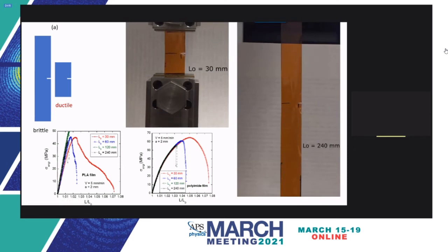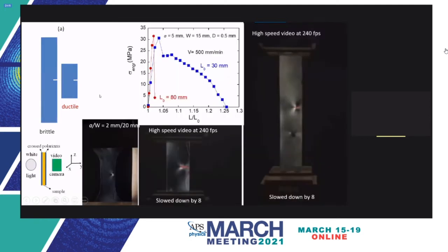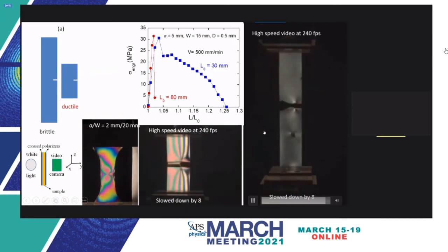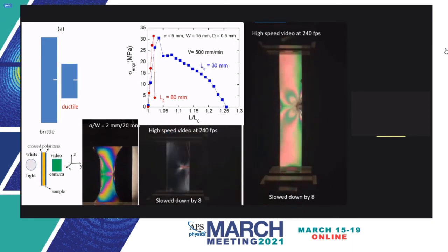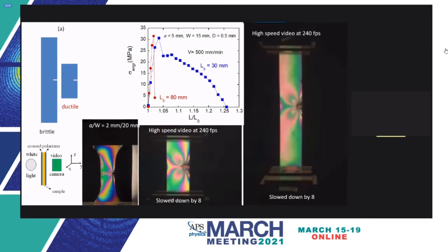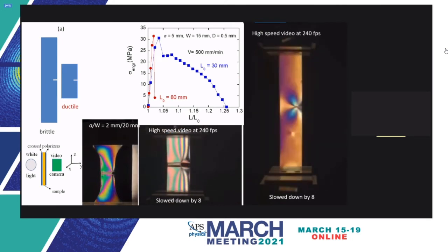Well, we have no time to explain why we think this is the case. So let's look at this problem a little further by taking a piece of polymer that can give us nice birefringence, with a cut. And here are the two movies showing that the long ones break, the short one does not. And this is the stress-strain curve for that. This is rather strange already. How come the length comes in? Because in the general discussion of fracture mechanics, this length will not come in.